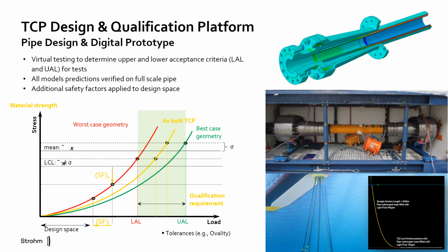The real expected performance, given that the need for manufacturing tolerances can never be fully eliminated, is generally in the middle of these two curves. A pipe with an as-built performance that is anywhere in between these two curves is considered to be acceptable in terms of our qualification. However, to continue our mindset of safety and robustness, the safety factor and resulting design space is calculated always from the lower acceptance limit, ensuring that the pipe will always have a very high minimum safety factor, regardless of whether it is at the low end or high end of the acceptance limit.